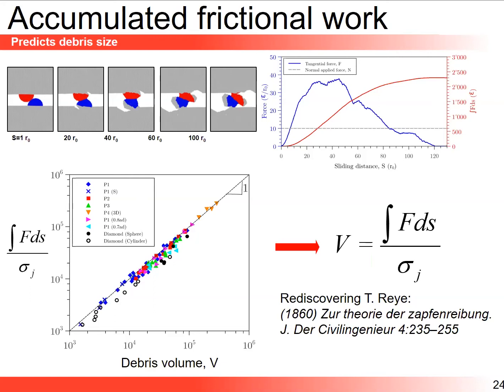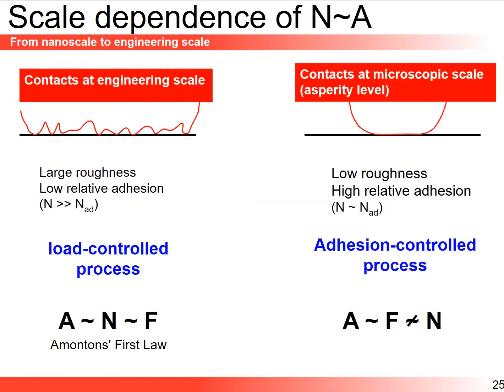There's a paper from a mathematician and geometer from Germany called Reye, who wrote a paper in 1860 in German. Very, very few citations, a handful of citations, much less cited than Archard. And in this paper, he recommends using the frictional work to predict wear volume. It turns out that if you are at the macroscopic scale, and if you can neglect adhesive forces, you are here on the left. Well, those two models are equivalent. Okay? But what our paper showed, it gives us a means to bridge between scales, to contact at the micro scale or atomic scale where adhesive forces are important.